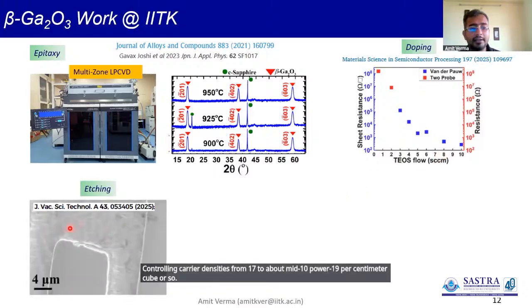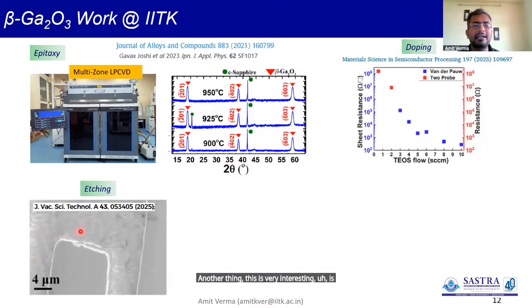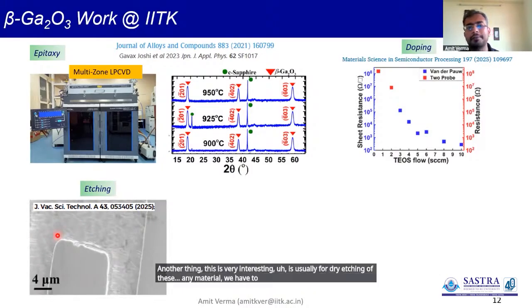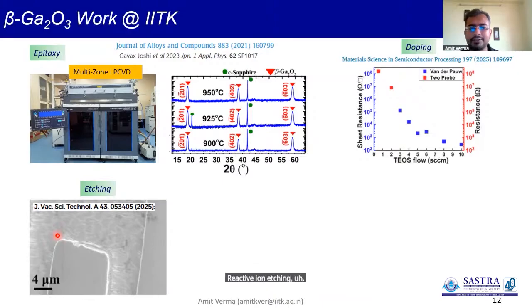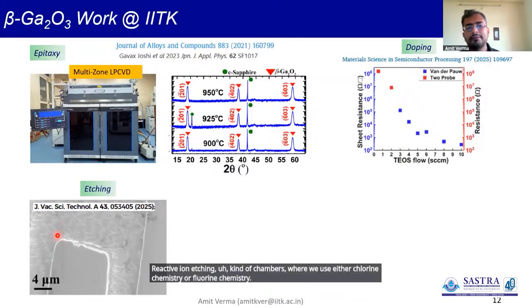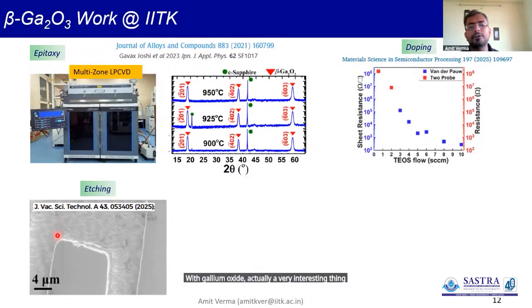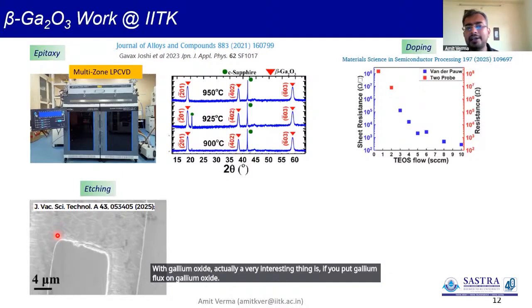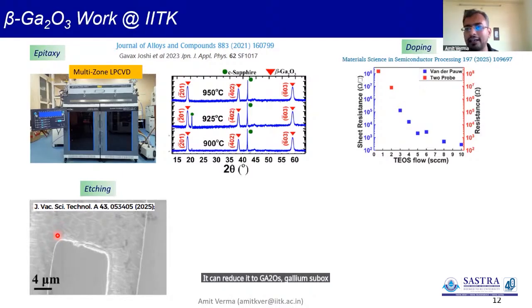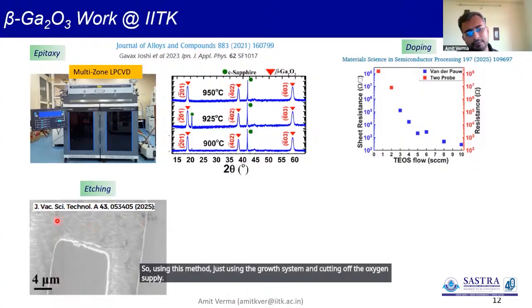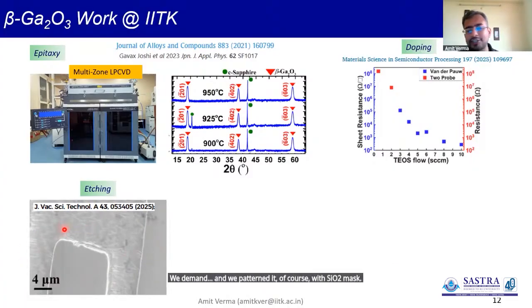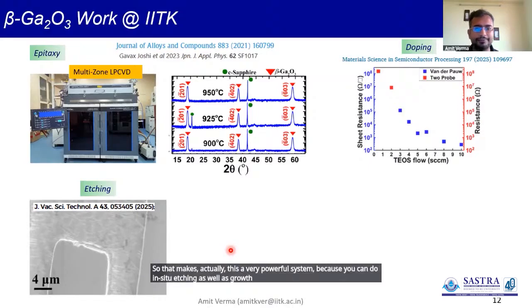Another thing, which is very interesting, is that usually for dry etching of any material, we have to use reactive ion etching chambers where we use either chlorine chemistry or fluorine chemistry. With gallium oxide, a very interesting thing is that if you put gallium flux on gallium oxide, it can reduce it to Ga2O, gallium suboxide, which is volatile. So using this method, just using the growth system and cutting off the oxygen supply, we patterned it, of course, with an SiO2 mask, and we demonstrated etching of these films. Essentially using the same system, we can do growth as well as etching by just controlling the precursor flows. That makes this a very powerful system because you can do in situ etching as well as growth in the same system.